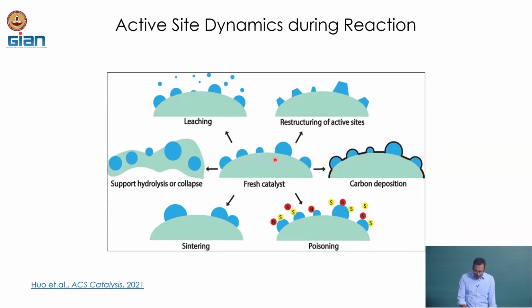So, we have the fresh catalyst, with a distribution of different sizes of active particles on the catalyst. Then it can restructure during the reaction, that is one. Number two, it can be leached from the surface of the catalyst, and there was a very beautiful example, if you remember: supported platinum catalysts are used as automotive catalysts, but because of the high exhaust temperature from your vehicle, some of this platinum continuously flies off from the support, and over time the platinum concentration on the surface goes down, and the catalyst deactivates.